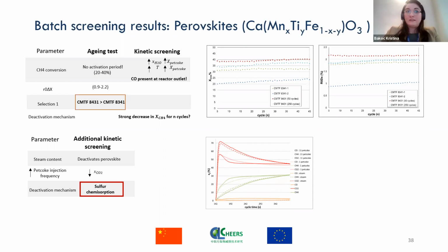What this has shown us is that upon multiple petcoke injections, there is certain sulfur adsorption on the surface of these materials. Since perovskites have low porosity, this leads to lower interactions on the surface of the material and overall lower activity. So in the case of petcoke study, they would not be the best candidate for further tests. However, with a different fuel, given the high values of oxygen transfer capacity, they could still be a very good candidate.